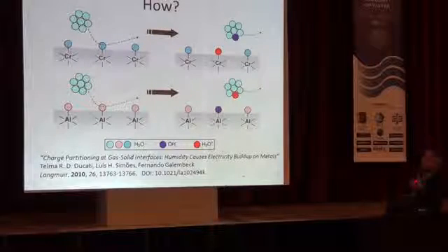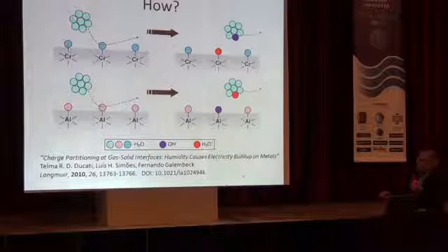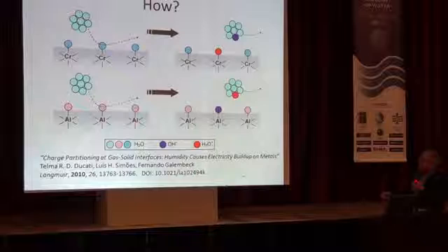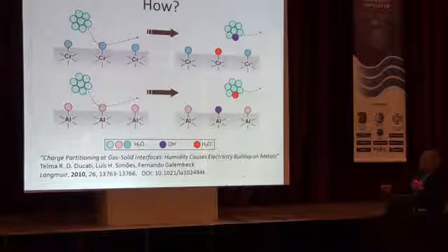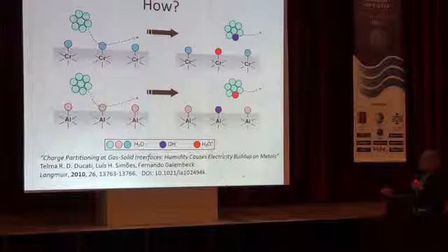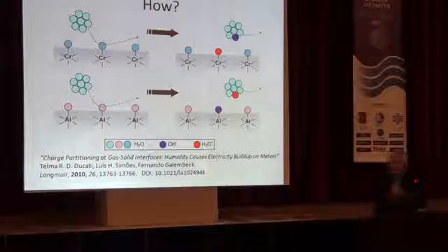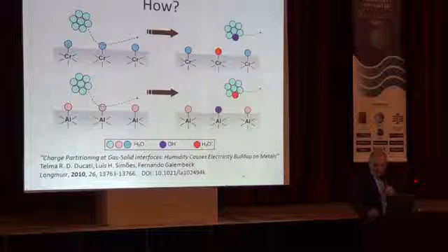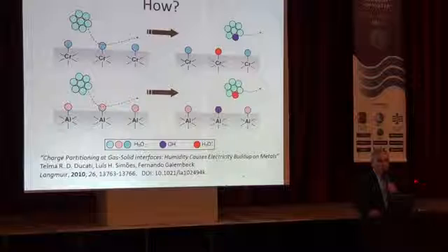So how does it happen? I detail here the idea. We have a cluster of water molecules that impinges on a basic surface, which picks up a proton, releases a negative water ion, and becomes positive, and vice versa for the aluminum surface. It's very important to recall that almost all these metals are always coated by oxide.